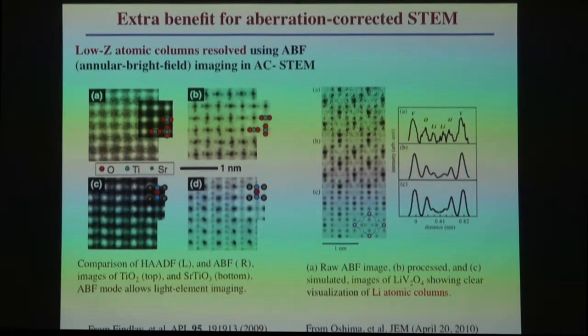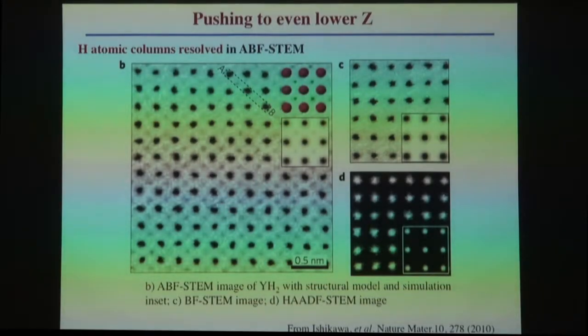So lithium atom columns can now be visualized. And taking things a step further, Ishikawa and colleagues were able to push down even to hydrogen atoms, or columns of hydrogen atoms. And here is the normal bright field image, here is the dark field image, and this is the annular bright field image. Here is the structural model. So the little green spots correspond to where the atoms are.